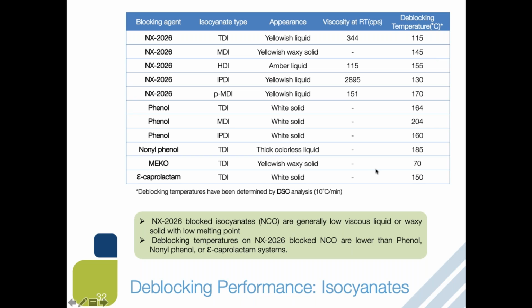And in this study, throughout the study, deblocking temperature determined by using the DSC analysis method. And of course, there is a various of other methods available. You could use FTIR or measuring actual performance to determine the deblocking temperature, and etc. So here, one thing to mention, MEKO, which is an oxime, these show much lower deblocking temperature. However, as I mentioned earlier, MEKO has high toxicity concern, and also it is very volatile component.